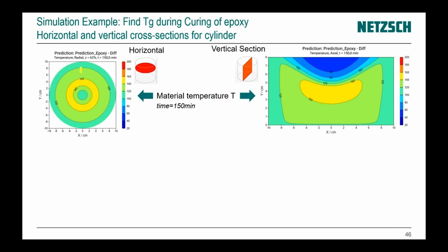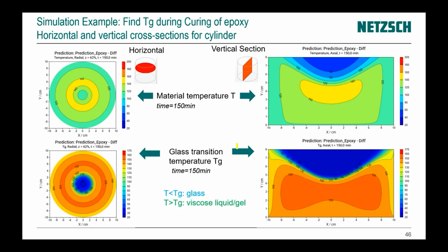And now what is especially for the curing process. Here we have a material for the cross-section, horizontal and vertical cross-section. And here we have a glass transition. It means that if you have from Kinetics Neo a kinetic model with diffusion control near the glass transition, which includes the vitrification process, then you can take this model, load it into Thermica Neo software, and make a prediction not only of the temperature and the concentration, but also of the glass transition temperature. And here, for example, we can see the glass transition temperature in horizontal and vertical cross-section.